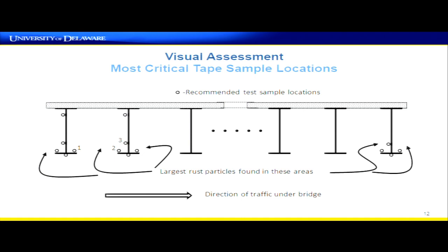If you were thinking of applying this, we looked at many locations along the bridge. The worst case scenario are the top surfaces of the bottom flange, and specifically of the exterior girders. If this is a highway overpass and traffic is traveling from left to right, in this first interior bay is where the largest corrosion particles were typically found. If you had a waterway crossing, there's more uniform corrosion. That's still a good place to sample.